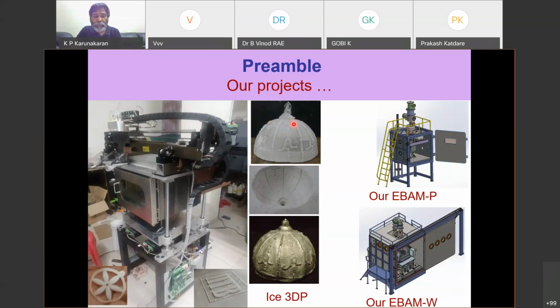How does it happen? See, the ceramic slurry will be at plus degree centigrade. It may be 10 or 15 degrees centigrade or room temperature. Ice is at 0 degree centigrade. So when you put ice in a flask and fill it with the slurry, rather than transferring the geometry to the slurry, the ice will absorb the heat from the slurry and then start melting. So we really struggled how to solve this problem because we were adamant that we want to use ice for casting.